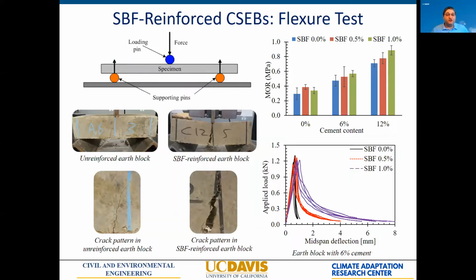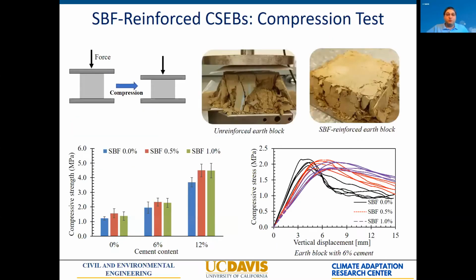We investigated this performance. I'm not going to describe everything in detail, but by doing flexural tests on the bricks, we found that indeed we could not only increase the strength of the material, but in particular we were improving the ductility of the material, which is critical to ensure safety of the structure. And this is evident both in the flexure test and in the compression test that we performed, where you can see how adding more sugarcane bagasse fiber has smoothed out the performance of the blocks.